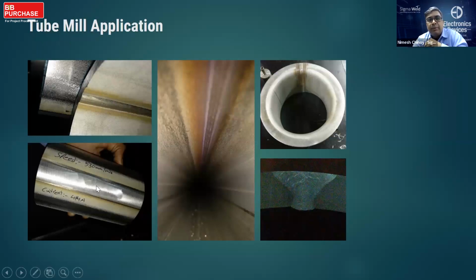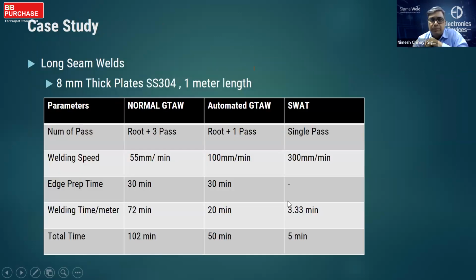This is for a 5 to 6 mm thick pipe. You can see the weld bead penetration. This is the top bead. Flaring test passed, and here's a micro of the same section.